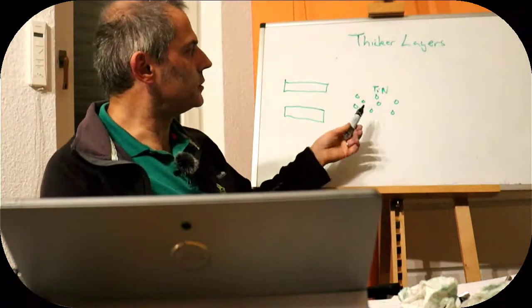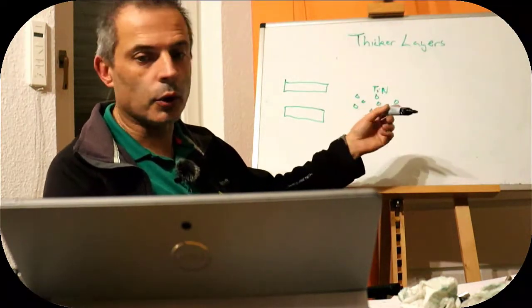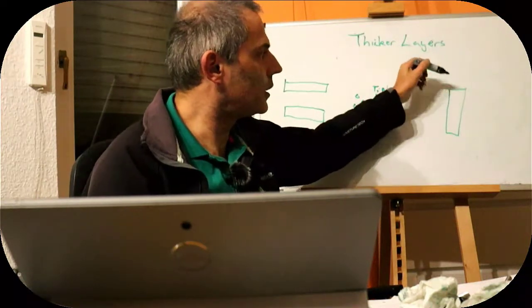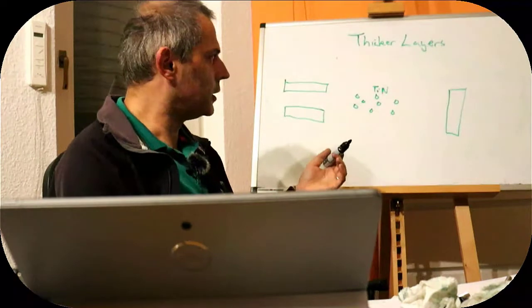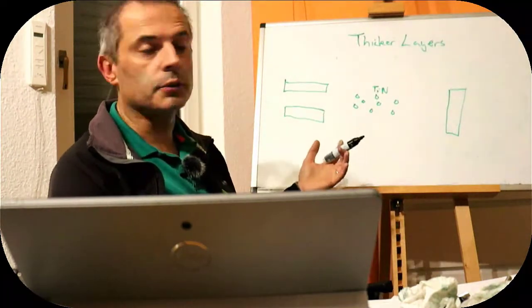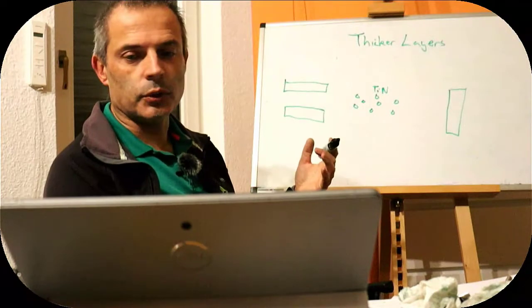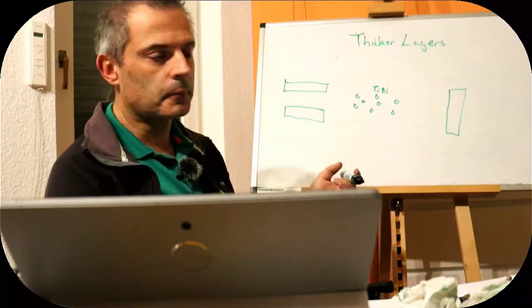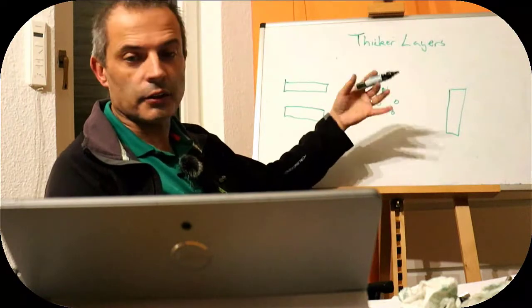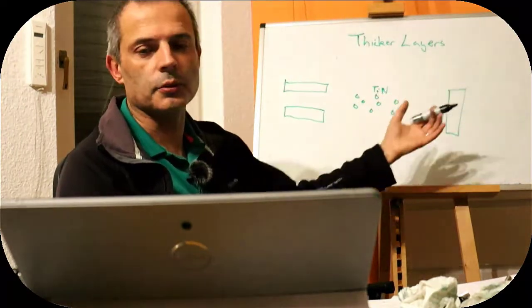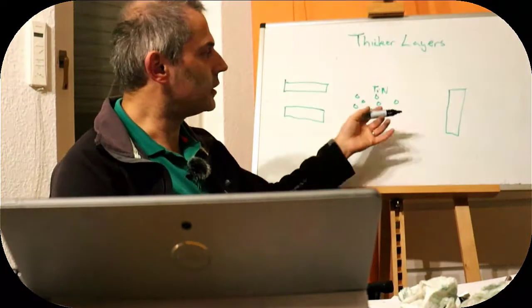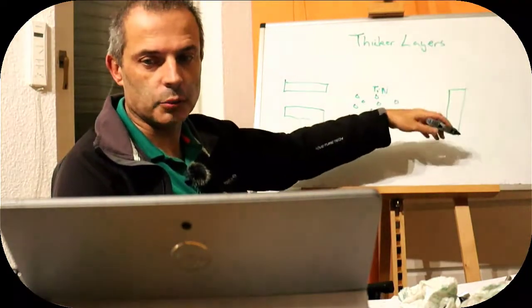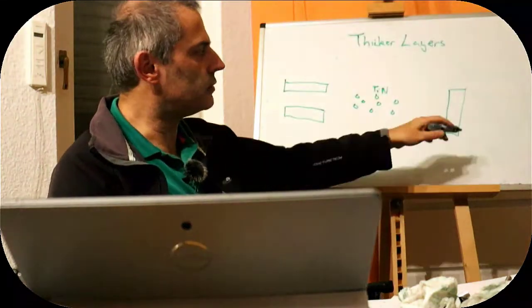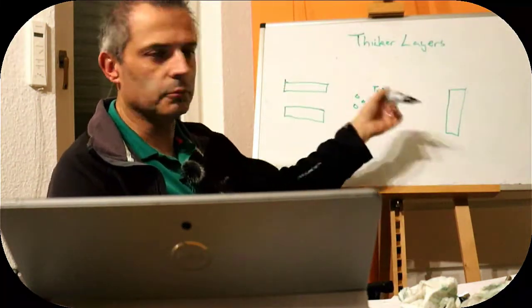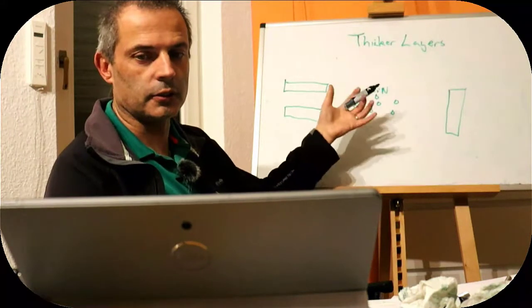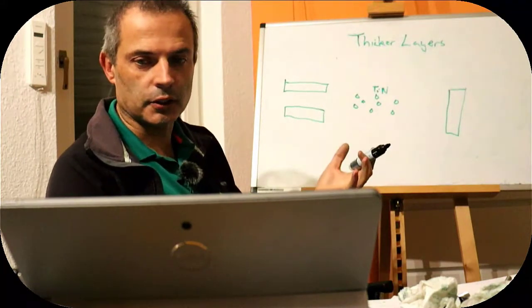So we're going to imagine some titanium nitride particles that we want to bond to something. We're going to make some kind of abrasive disc or something. We want to bond titanium nitride to the surface to make it very hard, and we need it to get there and bond to it. Obviously these are very hard particles, so if we shoot them into it, it's going to be like sand blasting, and they're going to work into the surface and just abrade this away. So that's not going to be any good. Even if this is made out of stainless steel or something, it's going to be drilled away in no time by the super hard titanium nitride particles. So that's not going to work.